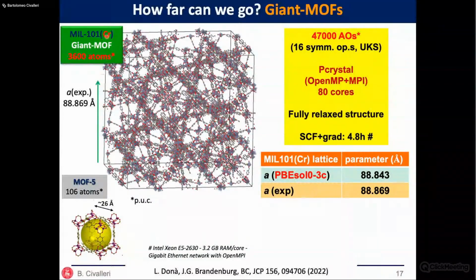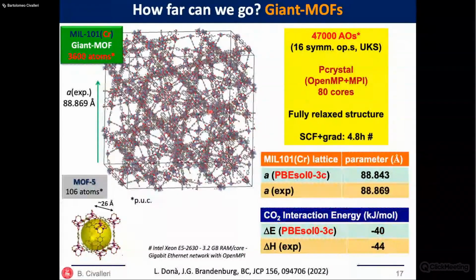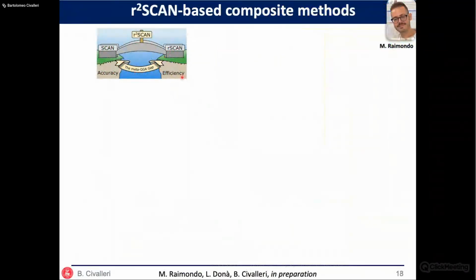If you notice, this contains chromium inside, so this is an open-shell system, very tough to study, also from a computational point of view. We then studied the interaction of carbon dioxide inside this material, and the predicted energy of interaction is in reasonable agreement with the experimental one, if you consider that this is a very huge and large system. I will be talking about MOFs later.